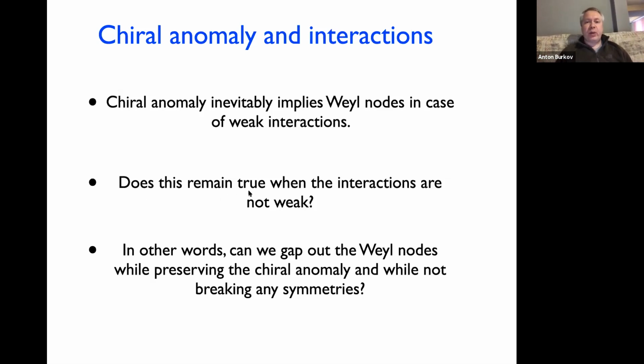We can ask the question, does this remain true when the interactions are not weak? In other words, can I gap out Weyl nodes while preserving the same value of the Hall conductivity, and while not breaking any symmetry? Why is not breaking any symmetry important? Because I can always gap out Weyl nodes by breaking translational symmetry, by creating a charge density wave whose wave vector is precisely the separation between the Weyl nodes. But that will just give me an integer quantum Hall insulator with a new reciprocal lattice vector, which is equal to the old separation between the Weyl nodes. So the question is, can I gap out Weyl nodes without creating this charge density wave?